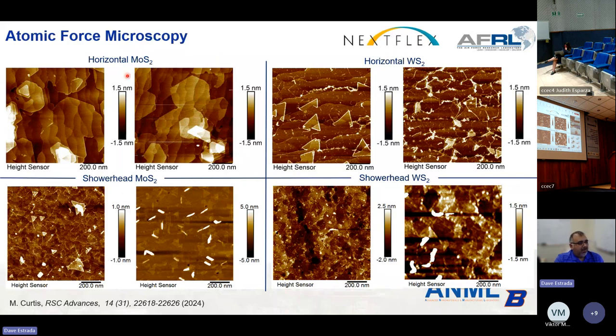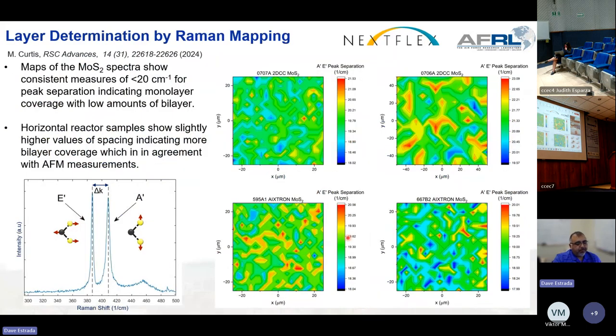good films. The horizontal quartz tube, you can tell from the AFM morphology, gives us larger crystalline domains of high quality, right? So larger basal planes on hundreds of nanometers. But in both cases, the WS2 is of poorer quality than the MoS2. We did some Raman mapping to quantify the percent of bilayer, multilayer coverage. The end result here is we have about 60 to 70% monolayer coverage, particularly for the MoS2, by